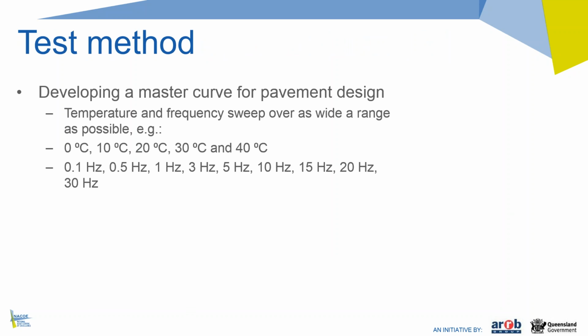So on the test method, if we're developing a master curve for pavement design, we want to do a temperature and frequency sweep over as wide a range of temperatures and frequencies as possible. How wide that range is will be predominantly a function of your equipment. The range of temperatures that you can achieve will depend on your temperature cabinet, and the range of frequencies that you can achieve in the test where you can have a robust load signal will depend on whether you're using pneumatic or hydraulic equipment. Hydraulic equipment typically is capable of imparting load signals at much higher frequencies than pneumatic equipment, but both can be used for this test method.